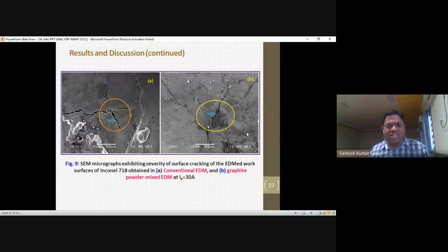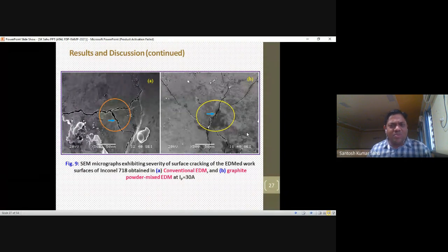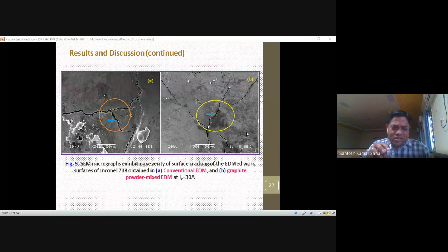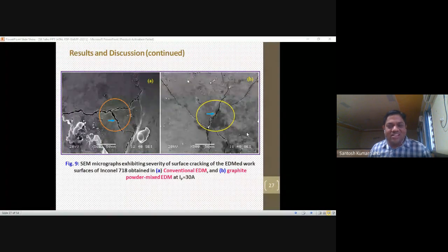Also you have to know that in traditional machining and unconventional machining, during machining some temperature also develops, and due to the temperature difference between the dielectric and the workpiece, cracks will be initiated. So for avoiding the localized increased temperature, the powder particle not only acts as a carrier of the spark, it also soaks some heat energy from the machined area, and the extent of thermal stresses developed at the machining surface was relatively less in magnitude.